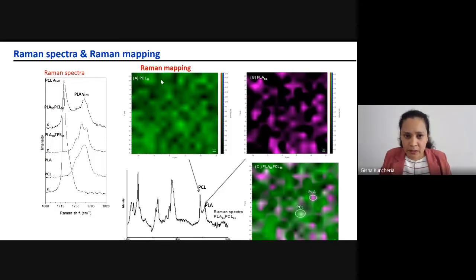In the Raman mapping, picture A is showing the pure PCL component distribution. Picture B shows the pure PLA component distribution. Picture C shows the binary blend, PLA and PCL. If you look at this big picture, it is clear the PCL is not allowing the PLA to crystallize out from the melt.